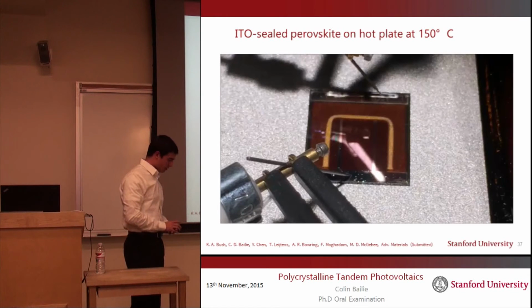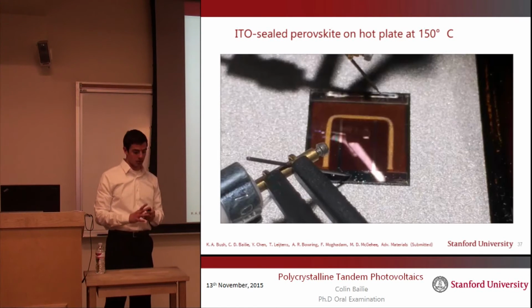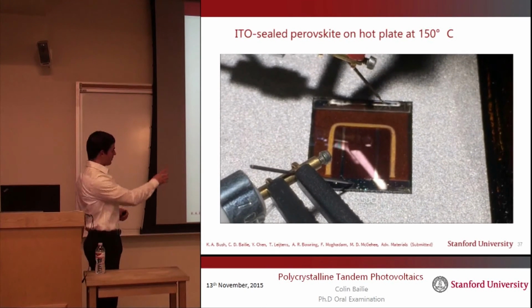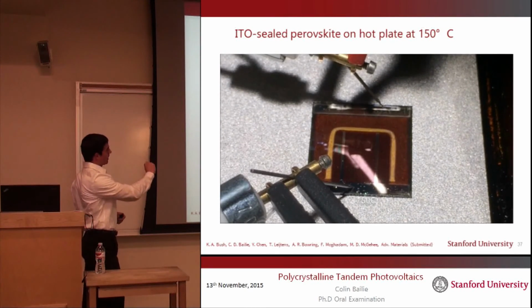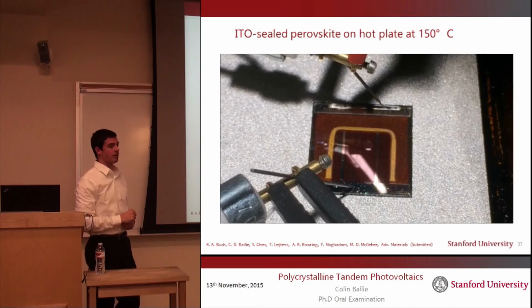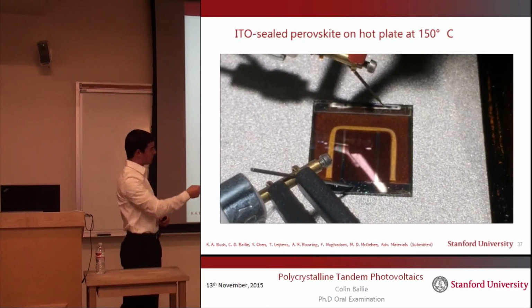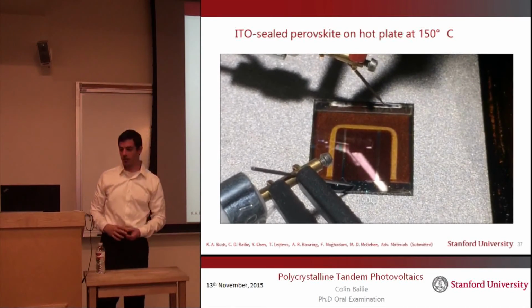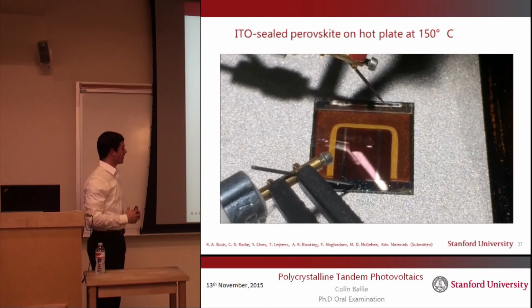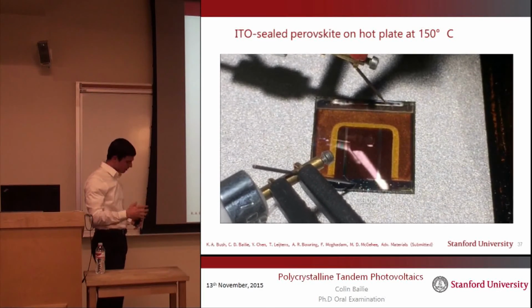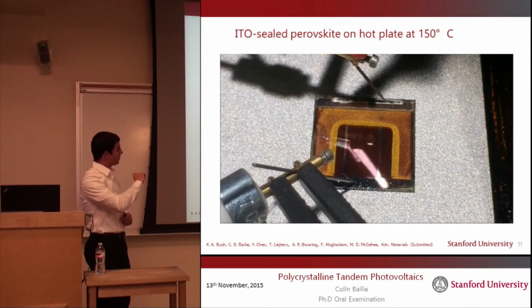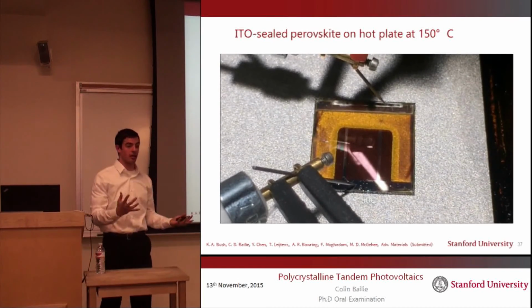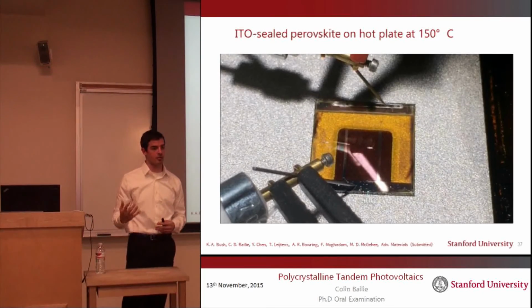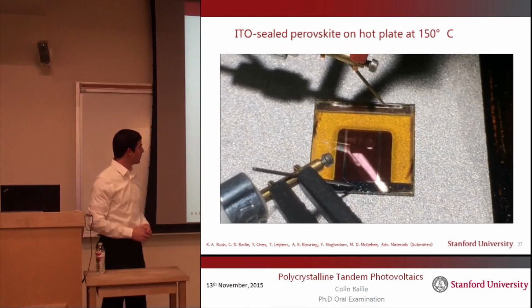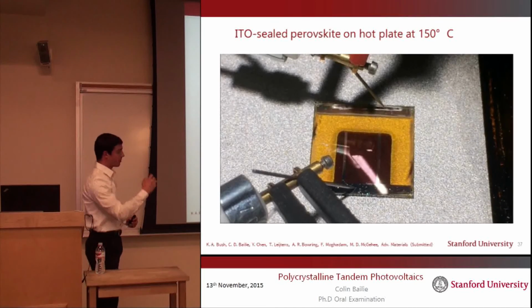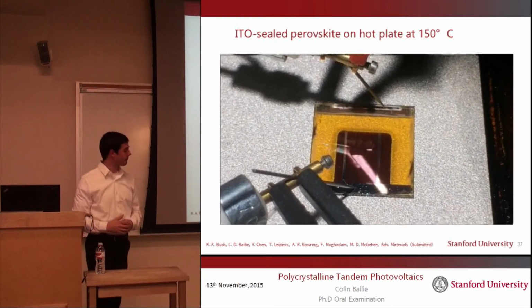Here's another video just to show visually how this ITO sealing works. This is a semi-transparent solar cell where this middle rectangle has ITO, and everywhere outside of this middle rectangle does not have ITO. And this is on a hot plate at 150 degrees C, and you'll see as time goes on, everywhere outside of the rectangle turns yellow, it's turning to lead iodide, which means the methylammonium is leaving, whereas the area inside the rectangle stays brown. It's still perovskite.